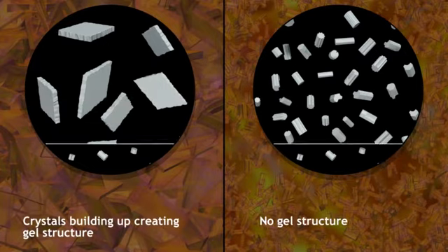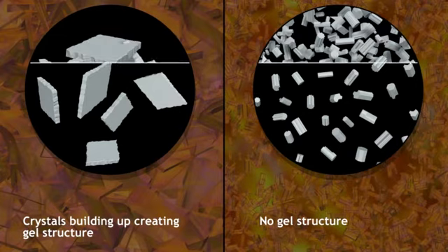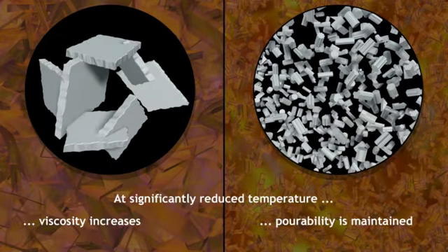Through the microscope, let's have a closer look. Once an oil has reached its cloud point, wax molecules first form needle-like crystals, then grow into plate-shaped structures, and, if temperature is decreased sufficiently, the plates will further develop to form a gel-like network structure. The oil ceases to flow in this gel-like state and viscosity increases significantly.